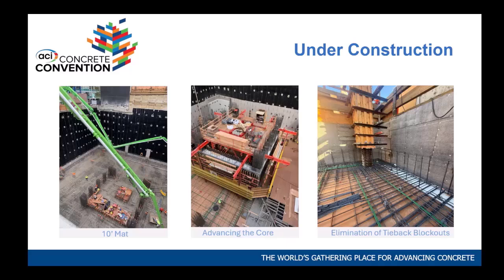The other thing we did is we created these column cages to lift, so you reduce the number of times you put these columns on site. If you have 16 columns, they staggered the columns. It's a cage that goes 2 levels. So for some of the columns, you only have to place half of the column every cycle of floors, because the other one is already sticking up. So it's 2-story lifts, and that works really nicely and speeds up the floor cycles by quite a bit on the typical floors above in the building.